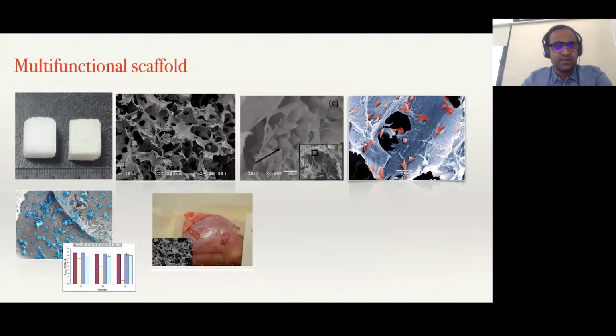So what we did over here is that we created a scaffold. If you look at the first image, the image on your left-hand side is actually a sugar cube. We used a salt leaching method to create a template of this sugar cube and then replicated it by putting a polymeric solution in it and washing away the sugar, and what you're left with is a replica of that sugar cube. And in the scanning electron microscopy image, you see that you get a very porous structure.